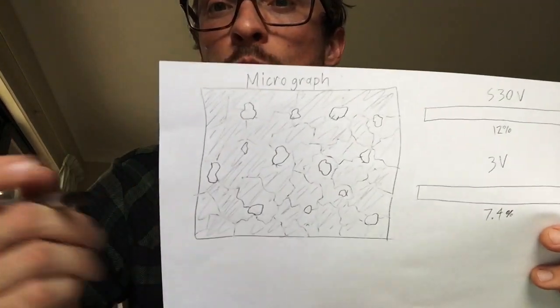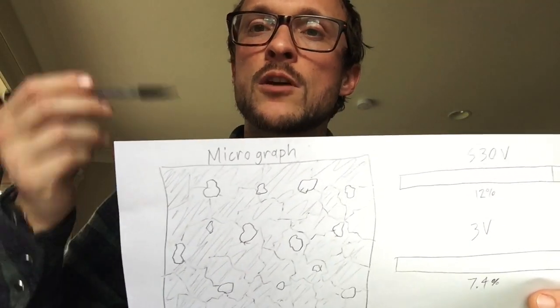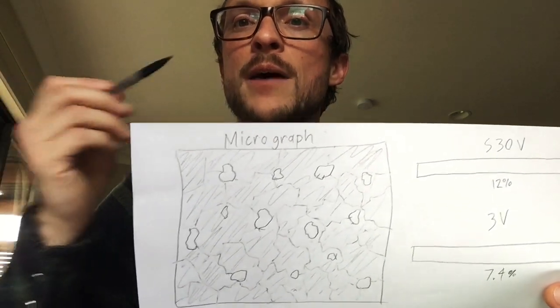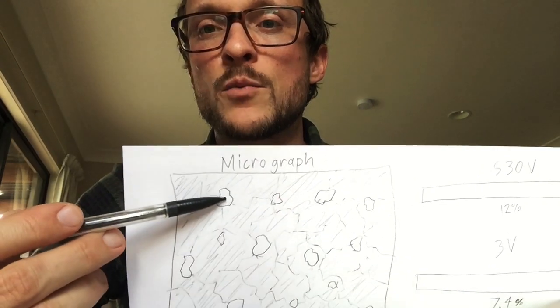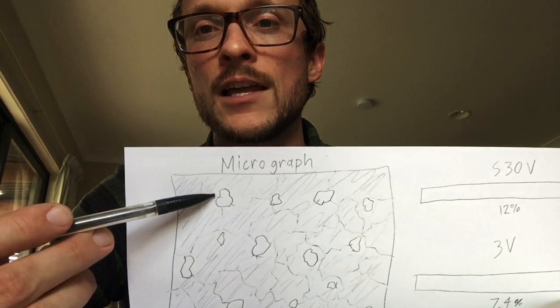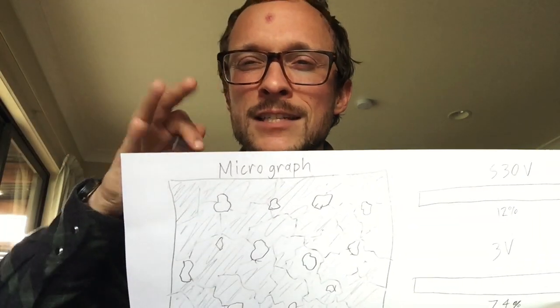Now, the grain structure changes can be somewhat changed by heat treat, but it's a pretty minimal change. The biggest thing that is causing you to lose toughness is carbides. It's filling that concrete full of rocks, so to speak. One thing that's been especially unhelpful in the steel world is that you need chrome. You need chrome to make the steel resist rust. But you get beyond a certain amount of chrome and it starts to want to bond with the carbon alone rather than the steel. And it will start to form these large and relatively soft and unhelpful chromium carbides.